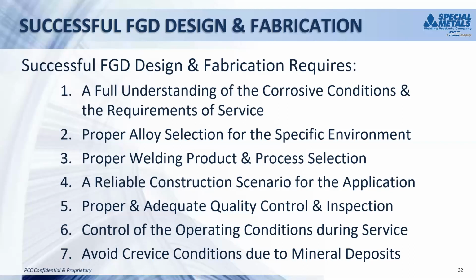We discussed 3 construction scenarios. All of those have been successfully used. It's basically just a matter of choosing the one that's most appropriate for your system and for which you have qualified welders. During the fabrication operation, proper oversight and adequate quality control is an absolute necessity. Welders should be qualified for the welds they're going to make, and certainly each of the welding procedures should be qualified as well. Once the system goes into operation, you need to be sure that the operating conditions are within the design criteria. We've seen cases where FGD scrubbers were operated out of control, and corrosion can occur very quickly. So operate the systems as they're designed.